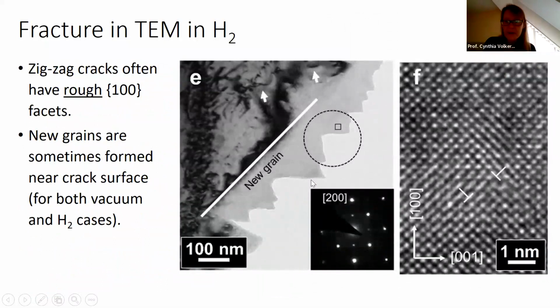Now, if we go in and look very carefully at these surfaces, you can see they tend to have 100 orientations, these facets. They're not crystallographically sharp, but the tendency to be lined up with the 100 surface is very prevalent. Sometimes we form new grains. That happens for both hydrogen and vacuum. I won't be talking about that much in this talk, but we see what we call the zigzag crack formation, and that's something we do not see in the vacuum case. So this is a distinct feature of the hydrogen fracture case.